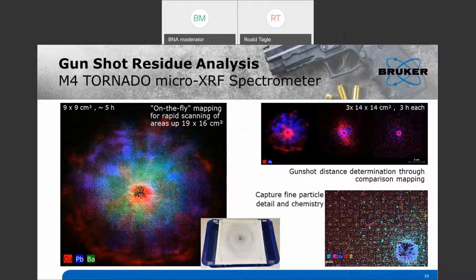All right. Another question is, what are the spatial resolution limits? Is the spot size of 20 micrometers the minimum area which we can focus on? There are two steps to this. The minimum step size of the instrument is 4 micrometers, so this is the smallest you can have the stage running. The measurement point is usually below 20 micrometers and slightly energy dependent. So for lighter elements, you have larger spots than for heavy elements.